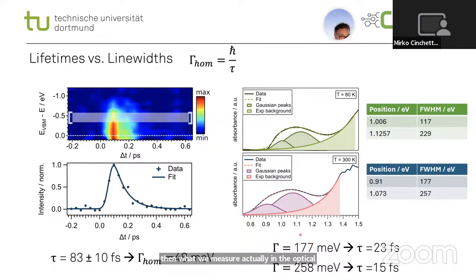You see here we have a line width of above 250 milli-electron volt. So why is there this discrepancy? This can have two reasons. Either the optical measurements have additional inhomogeneous broadening. You have to consider that the optical absorption experiments are more bulk sensitive, while the photoemission is surface sensitive. So there might be some mechanism of inhomogeneous broadening in the bulk, or there could also be some additional quasi-elastic scattering channel that we do not detect in the photoemission experiments.